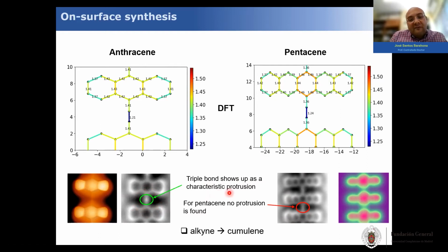You know that triple bonds have cylindrical geometry. So when you go with the microscope, with the AFM tip, and you find the triple bond, you have to go up. So it seems brighter, which is not the case for the pentacene, where there is no bright spot. We confirm this by DFT calculations. You can see here that you have a very short triple bond of 1.21 Å, whereas in the case of pentacene, what should be a triple bond is now longer, but what should be a single bond is shorter. Also, the structure of pentacene is less aromatic and more resembles a quinoid structure. So what we have in the case of anthracene is aromatic and triple bond, and in the case of pentacene is quinoid and cumulenic.